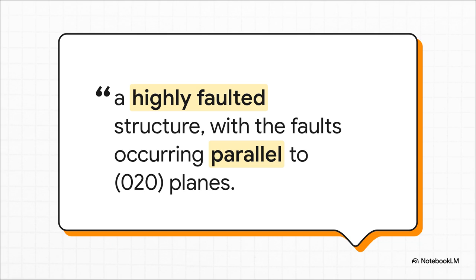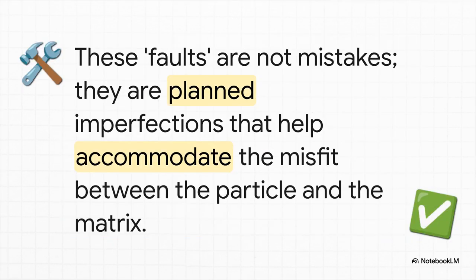And this is where it gets really, really cool. The researchers saw, and I'm quoting directly from their 1991 paper, a highly faulted structure. Now that sounds bad, doesn't it? A fault? An error? But it turns out that's actually its secret weapon. Get this, that fault isn't a mistake at all. It's a planned imperfection. It's this tiny repeating structural flaw that actually lets the boron needle relieve stress and line up even better with the titanium. It's like a clever little atomic hack that makes the whole thing stronger. It's a feature, not a bug.